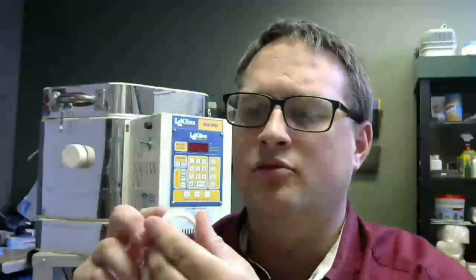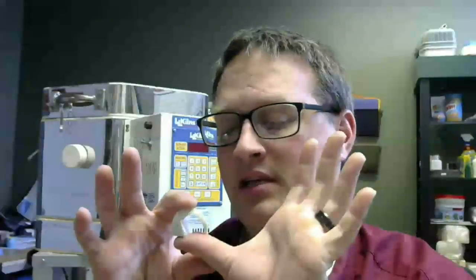with a programmer. How important is it to do a cone temperature test and how often? That's for Jack Wrightham. Jack, we do our test cones, and probably every 5 or 6 firings, we'll put a cone in just to make sure that it's firing accurately. So it is pretty important that we keep our firings calibrated. So we fire to a hot cone 6. This cone here is a cone 6, and it's just touching. And that's what we fire to here at Clayscapes.